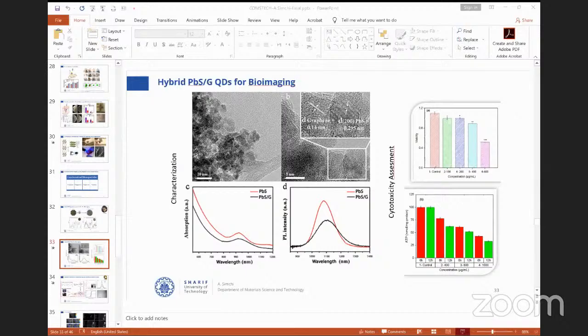And you see in the lower pictures that the material still shows photoluminescence intensity even at 1100 nanometers, which is extremely helpful for bioimaging. We did a lot of examination on cytotoxicity and on biodistribution, and we have shown that at a specific concentration, it is possible to use it for bioimaging. However, many of our partners are afraid to use these materials for bioimaging because of the lead.